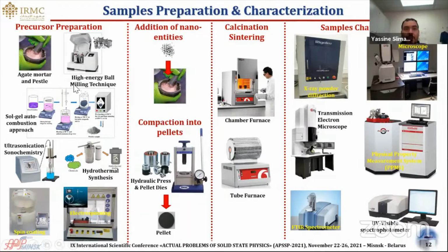Then the obtained superconductor precursor will be grinded, and different amounts of nanostructural materials will be added to the precursor. They will be compacted into the form of pellets. Then the different products, either the precursor or the mixed ones, are subjected to different steps of calcination and sintering at high temperature.